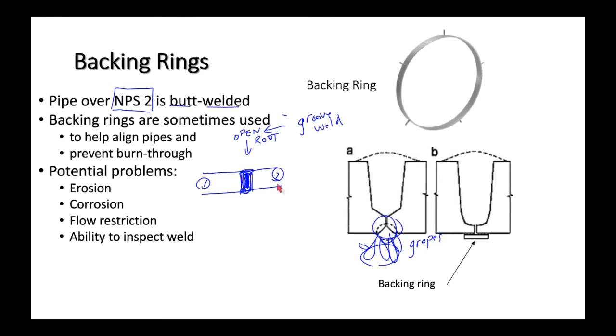And that's not enough yet. Then the weld inspector is going to cut this up into coupons and give it a tensile test, and a bending test on the root, and bend it on the face, and then maybe send it for radiographic examination as well. Once it passes all that, they give this person a pressure welder certificate. The person welded a groove weld to an open root, so this guy or gal can weld pretty much anything. When we get into welding, we'll go into more of the nuances about what exactly a welder can weld.